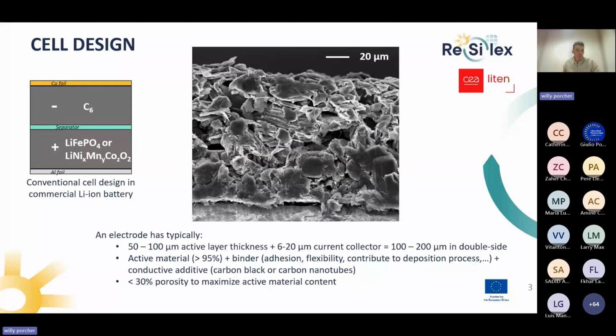So going now inside the cell, we have both electrodes, which are deposited on current collectors, copper for the negative electrode and aluminum for the positive electrode, and separated by a separator to avoid a short circuit, with only lithium exchanged between both electrodes. An electrode typically has a 50 to 100 micrometer active layer thickness with the thinnest possible current collector. We deposit the active layer on both sides. That means in the end a 100 to 200 micrometer double-sided electrode.